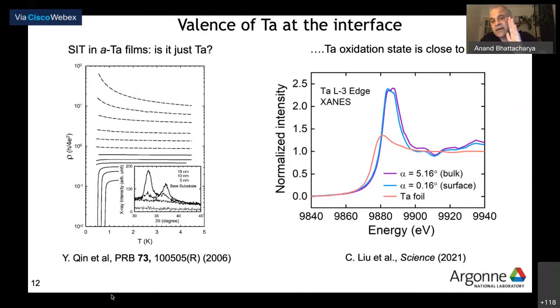And in fact, if you went in at the glancing angle, you see that there's a little bit of reduction of the tantalum. The edge moves a little bit. So perhaps that's what we're seeing, some doping at the surface of our sample. All right, so it's not that.